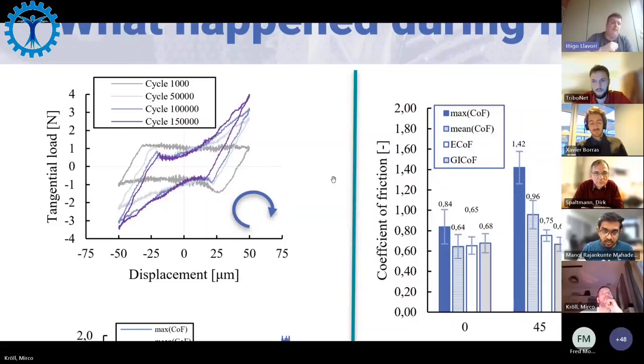In the streams where the velocity is lower, you accumulate a lot of points there, and in that case the values might be really low. So in the averaging process, those values average it down. So the mean value, just to take the average of all values, is not a good approach, because you are integrating in time, which is not good.